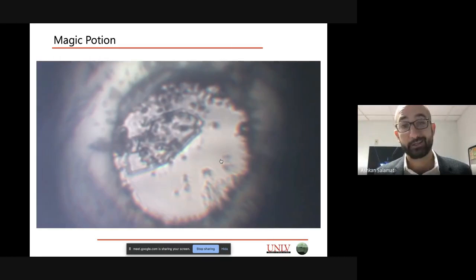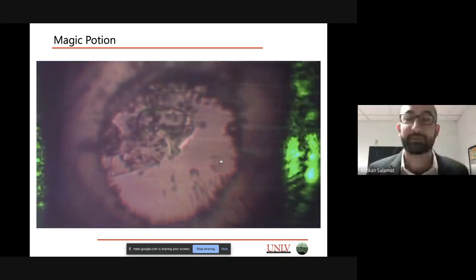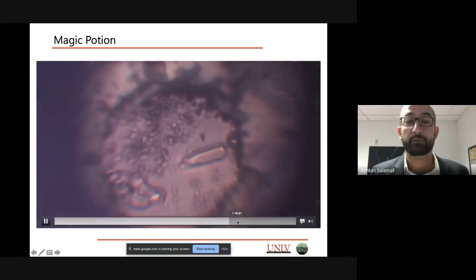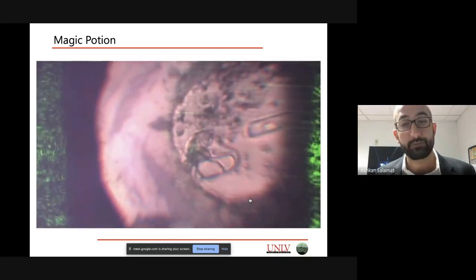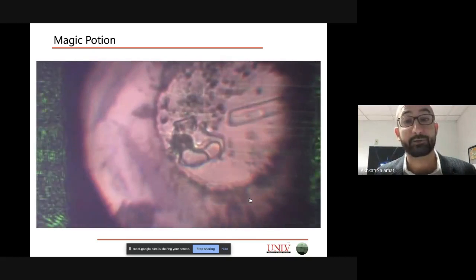We're able to shine green light onto our material and initiate a photocatalytic reaction. So we can put our materials into this handheld device, and using just green light, we can initiate a photochemical reaction. As you can see, the black soot is disappearing, and in its place appear these transparent crystals. I'm just going to quickly fast forward. As we walk the laser around, we can initiate this reaction. What's actually occurring on a deeper level is that we're forming S8 polymers undergoing a radical reaction, which in turn sets off a chain reaction, which leads to the formation of hydrogen sulfide, methane, and hydrogen. And we end up making a Van der Waals crystal.